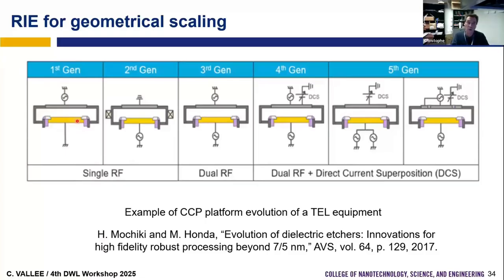When we found the RIE and we can use ions, we modify. Now we apply the power to the substrate to put some energetic ions. And after we started to have dual frequency generators, and after the design is modified, now they have some superposition of DC voltage for ballistic electrons. You have two different frequencies at the bottom.